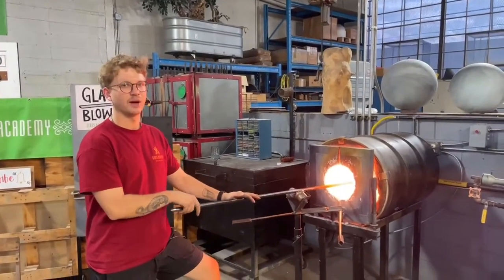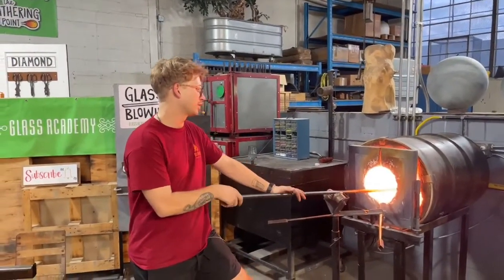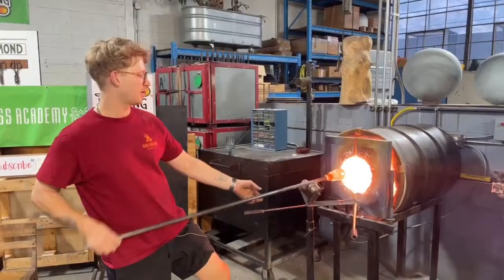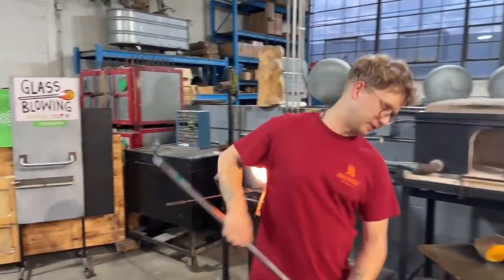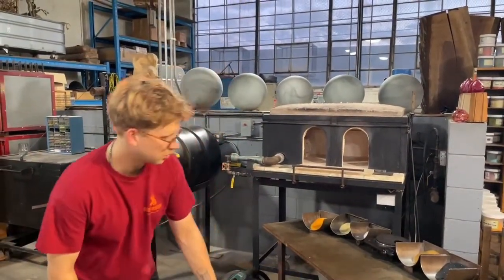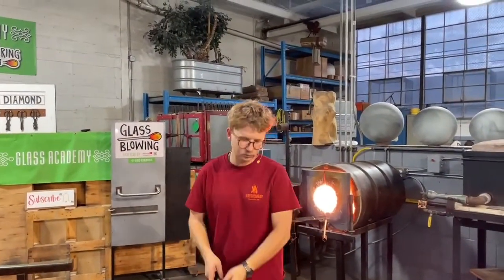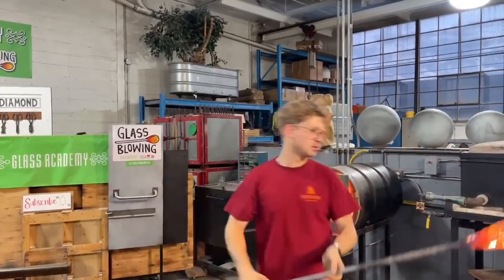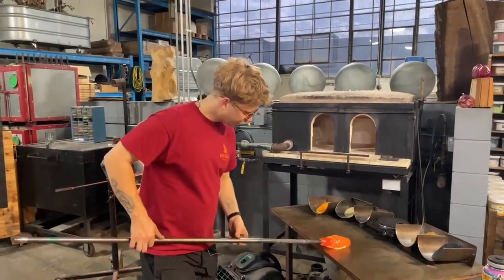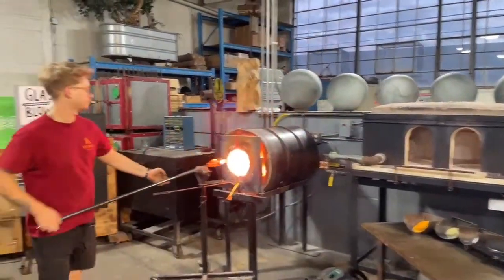I wasn't going to talk about it, but I appreciate you bringing up that every time you do encase glass is an opportunity to trap bubbles, and I particularly am not anti-bubble, but when you're doing something crystal clear like a pumpkin like this, it's a great point by Oliver that any jumbo bubble sitting in here would be very obvious. Even though, since we got other glass blowers in there, depending on the conditions of the furnace that you're using, bubbles are one thing, but then also you can get a stone or a rock in that glass as well. And the more glass you're gathering, the bigger chance for that. So that's a fact. We're pretty fortunate with these brand new furnaces. This is a good time to be practicing encasements.